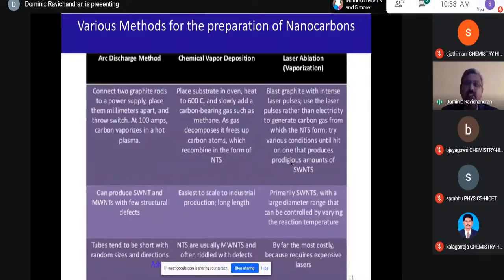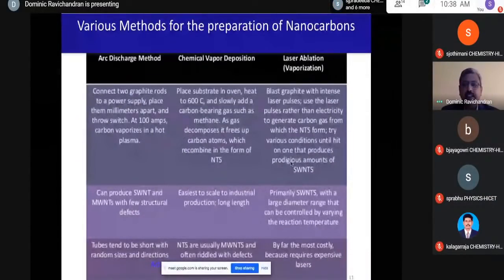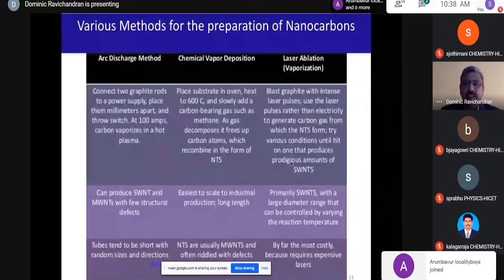And coming on to chemical vapor deposition, the substrate is kept in an oven and heated at 600 degrees centigrade and slowly added carbon bearing gas such as methane. As the gas decomposes, it frees up the carbon atom, which recombine in the form of nanotubes.